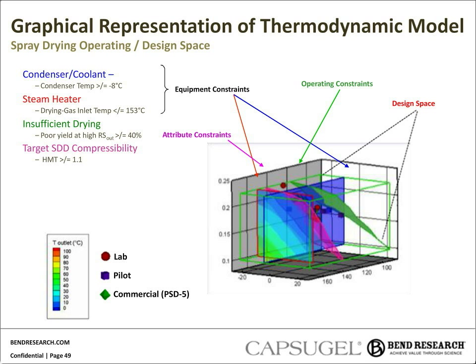space. In this example, we show equipment constraints on maximum inlet temperature, that's the red plane, and equipment constraints on minimum condenser temperature, that's the blue plane. Both of these constraints are based on plant utilities and actual equipment capabilities. An operating constraint at 40% relative saturation is shown with the green plane. So beyond that plane, the drying process is just too wet and there isn't enough driving force for drying, leading to spray drying and low yield. So you can see that there are no actual experimental runs beyond that because the yield starts to drop off in the back right-hand corner of the three-dimensional space.